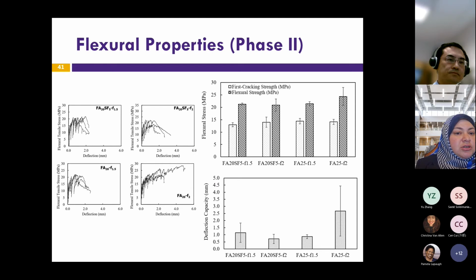These are the flexural results as well. We can see that the mix with 25% fly ash and 2% fiber was the best performer, and it experienced the highest deflection capacity.